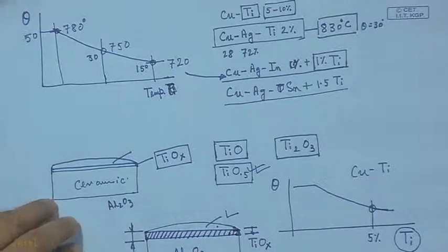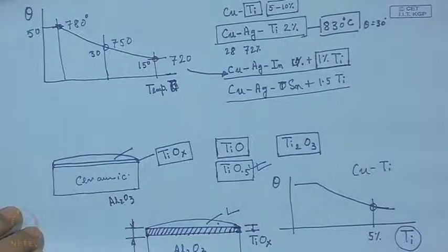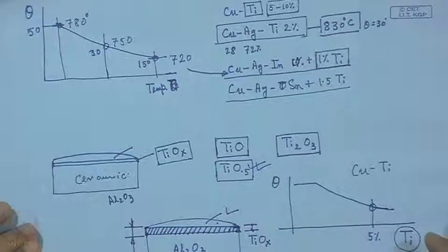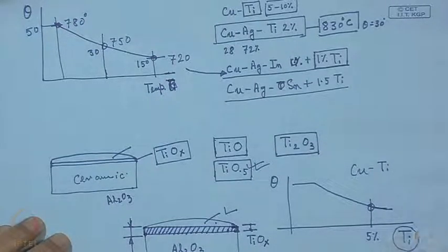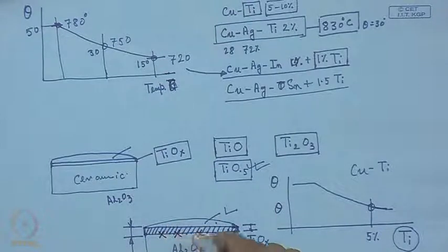It is not only the question of aluminium oxide, it can happen with silicon carbide, silicon nitride and other materials, boron nitride, boron carbide. So, the main objective in wetting, in deposition of a coating by spontaneous spreading or wetting, is not just getting a good value of this theta, but also to have good adhesion at this point. And this calls for a fine or very thin reaction layer, which will not affect this stress differential or change in volume at the interface because of the large size.